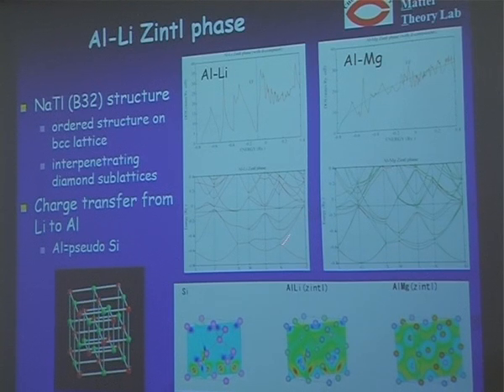And actually, this is the result. You see the very deep pseudo gap at the Fermi level. And if you look at the band dispersion curves, we have a band dispersion very similar to the silicon diamond case.